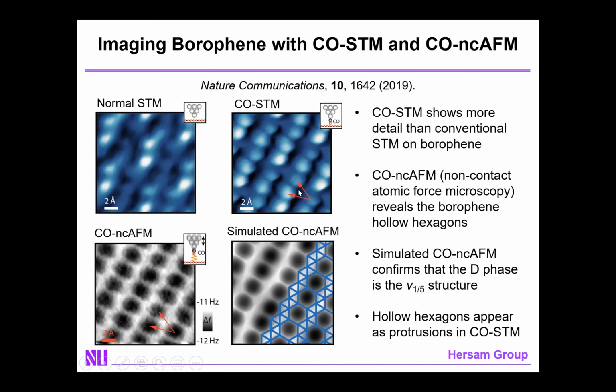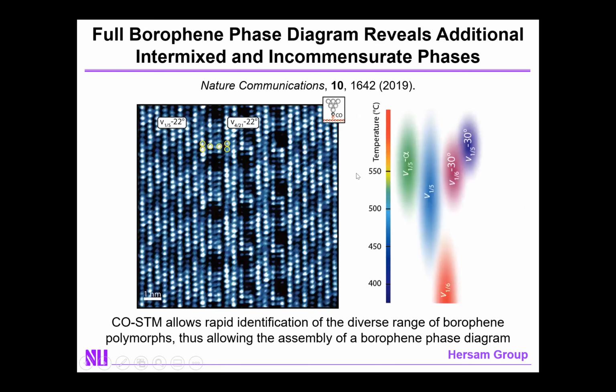This also allows you to interpret the STM image, and what you can see is that the protrusions in CO STM correlate with the hollow hexagons in the real topographic structure. And therefore, you can utilize CO STM to deduce other possible arrangements of boron atoms in a 2D lattice. And indeed, over the subsequent years of study, we were able to map out several different borophene phases, the V1/6 and